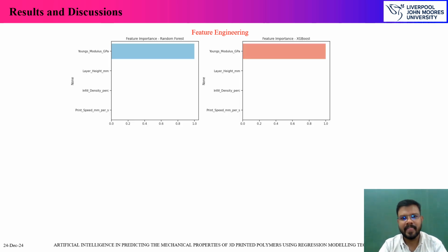So in this context, we now start with the feature engineering. That's where the elimination or the retention of the features comes in. As discussed earlier, we have four features: the layer height, print speed, infill density, and the Young's modulus value. From feature engineering, which is done through random forest and XGBoost, yet again it's been proven that the value of Young's modulus plays a vital role in determining the ultimate bending strength. However, we could see a minimum or the least contribution from all the three subordinate factors. The same thing is also noticed in the XGBoost model. You could also see the least contribution from all the three factors apart from the Young's modulus of the material that is being used.